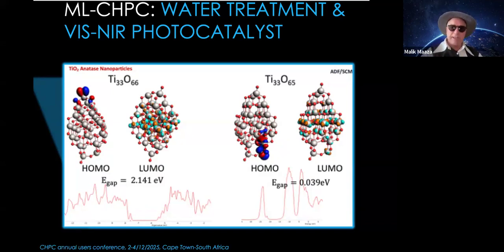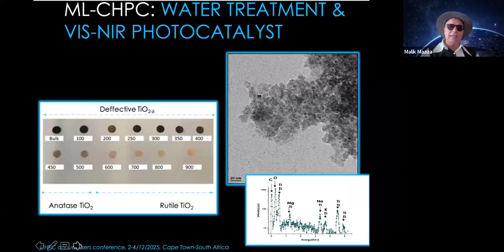And as you can see, the density functional theory shows us that you can reduce the band gap from 2.14 to nearly 0.039 electron volt. What does it mean? While the standard TiO2, the white one, is active only under UV radiations, the same titanium dioxide with the defects on the surface, as predicted by the modeling, DFT and molecular dynamics, will be active in the visible range, and that is the case.